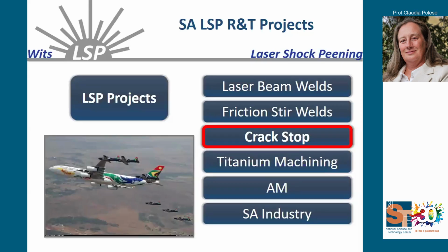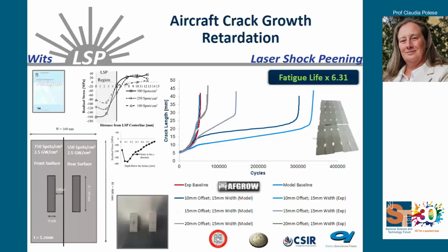Unfortunately, in aircraft it's very common to have a lot of small cracks. People don't like to hear that when they fly, but unfortunately it does happen. The important thing is that it's not a crack out of control. A lot of the fracture mechanics work that we're doing is making sure that we assume a crack is there, but make sure it is not propagating too fast. That means it's still safe to fly,